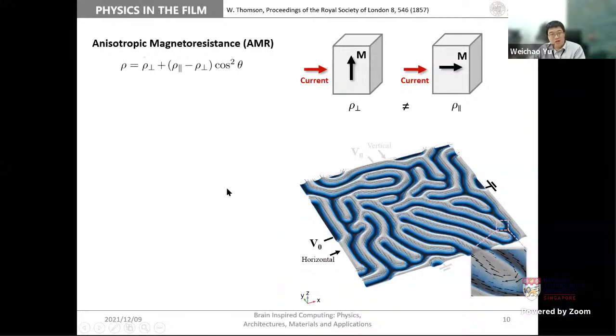What is going on? What's the physics lying in such a physical system? Firstly, we have anisotropic magnetoresistance, AMR, which means that when the current flows through the magnet, the resistance is different depending on the alignment of magnetization. In the presence of AMR and such a complex texture, we will have a general Ohm's law, where the conductivity is no longer a scalar but a tensor, which depends on the specific magnetic configuration.